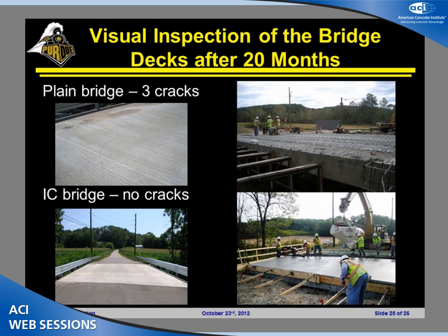Now, does this mean that you should expect no cracking on every internally cured bridge deck? I would say no, that's pretty unrealistic. But what we can definitely see here is there's a substantial reduction in the number of cracks that are forming in those particular cases. Same crew, same plant, same location. The only thing we did was we replaced about 25% of the sand with lightweight aggregate.